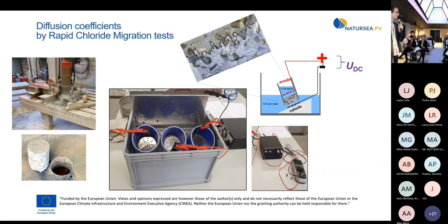Here is how the method looks in our laboratory at TU Darmstadt. We first drill the cores, and this is called the rapid chloride migration test. It's a standard test where we use voltage, because otherwise natural diffusion needs a long time. We use voltage to speed up the chlorides, because chlorides are negatively charged, so they are attracted by the anode.